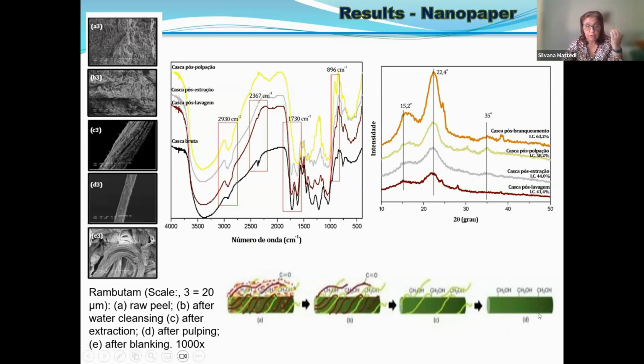We also tested hydrogen sulfate ionic liquids, the ammonium sulfate and different kinds of ammonium. But we were interested in producing a rugose surface for adsorption, so it was not as good as acetate materials. However, here we are interested also in obtaining the cellulose nanocrystal, so sulfuric acid is more indicated.